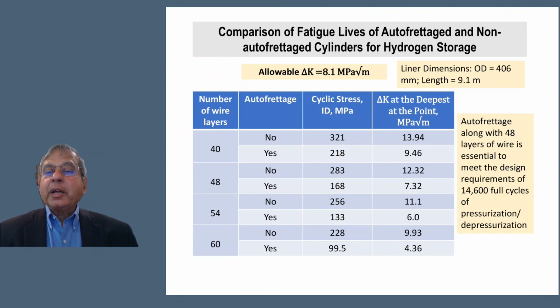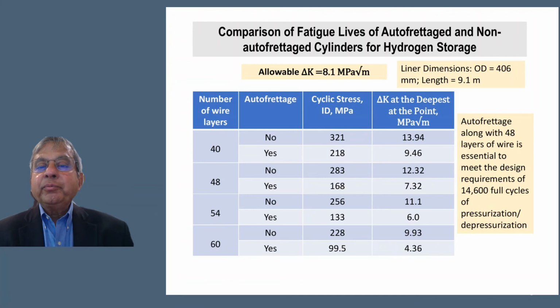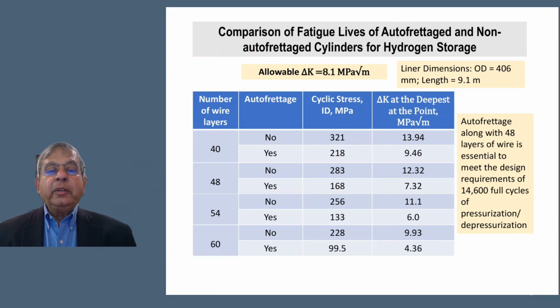On the other hand, the autofrettage pressure can be 2-3 times higher than what you would generate from just the wire tension, and it can reduce the maximum stress in the liner very significantly. So if we look at vessels that have been wound with 40 layers of wire, 48 layers, 54 layers, and 60 layers, and at autofrettaged and non-autofrettaged vessels, where no means it has not been autofrettaged and yes means it has been autofrettaged.